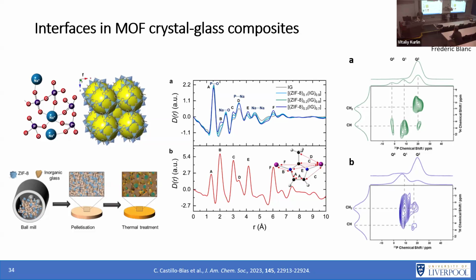And it's very often used in combination with a bunch of other techniques, whether it be powder diffraction, crystal diffraction, pair distribution function, etc. So you don't need to worry too much about what this study is, but essentially it's an inorganic glass and a ZIF composited together. Then Fred did this beautiful NMR, and essentially this was on a physical mixture, where the two things were just mixed together. We can see that there isn't very much interaction between the ZIF and the inorganic glass. And then obviously you've got this lovely interaction between the ZIF and the glass in our composite material.